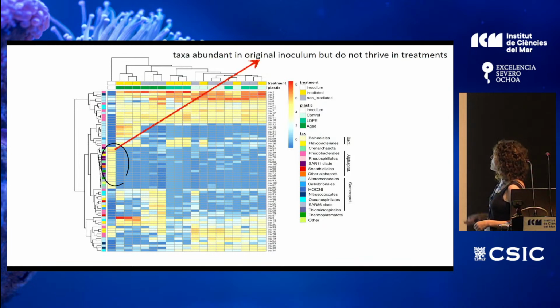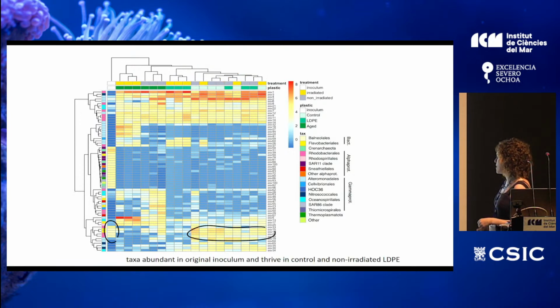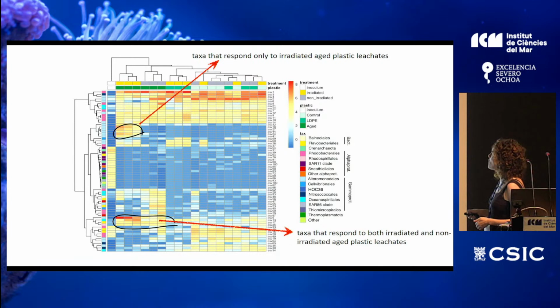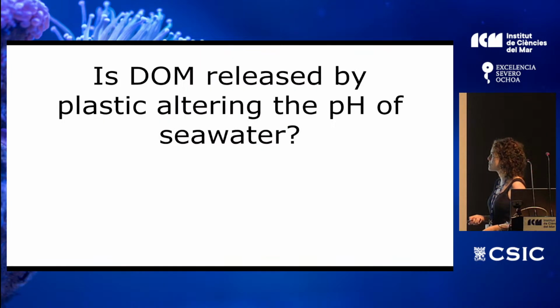So what we found, for example, is that here we have taxa abundant in the original inoculum that do not thrive in the treatment. But then here we have taxa abundant in the original inoculum that thrive in control and non-irradiated LDPE. More interestingly, here we have taxa that respond only to aged plastic, that was the leachate that was previously irradiated, or here taxa that respond to the aged plastic, both previously irradiated or not. So there are some differences in this, and we are now working with these results.